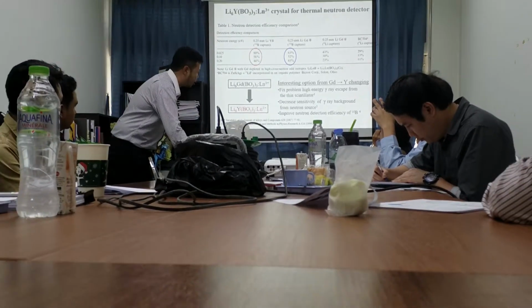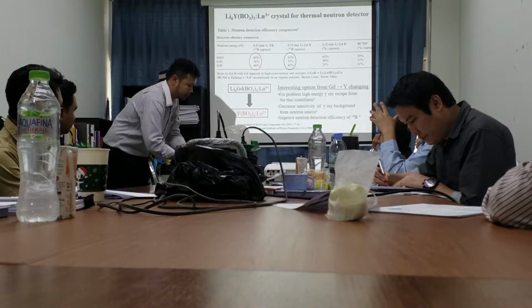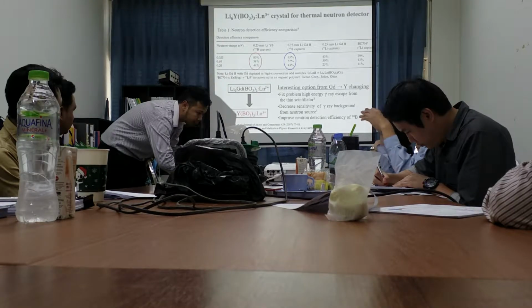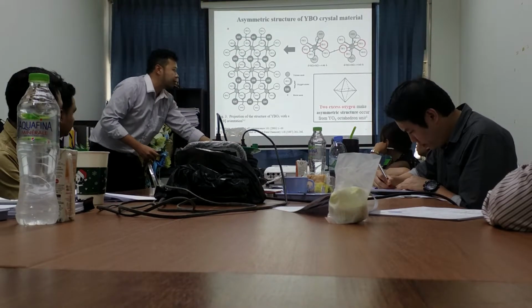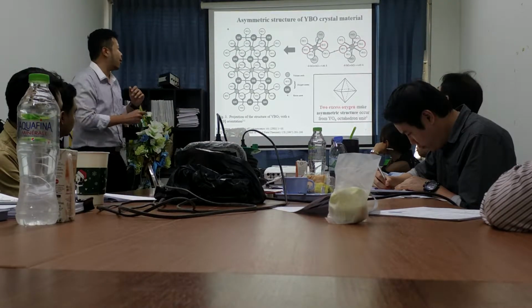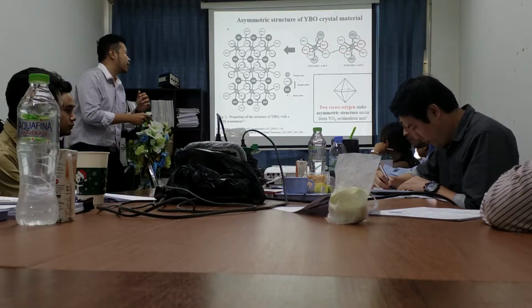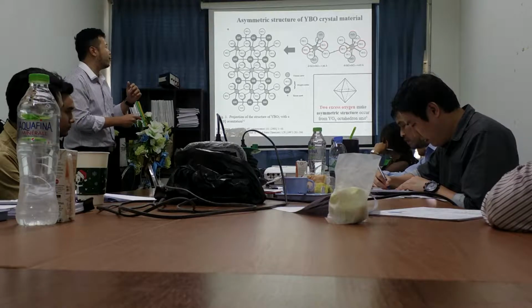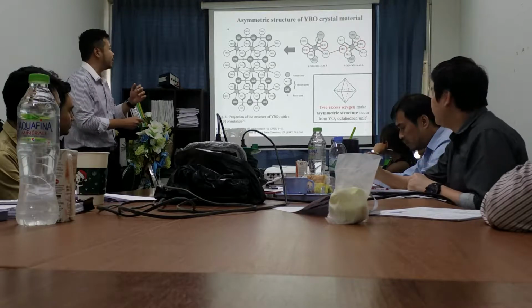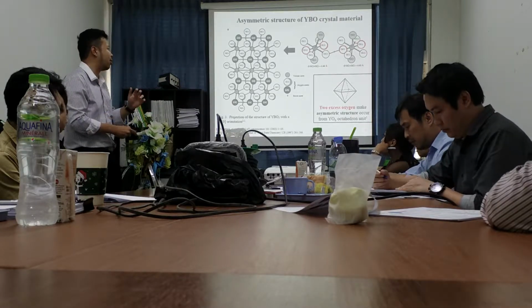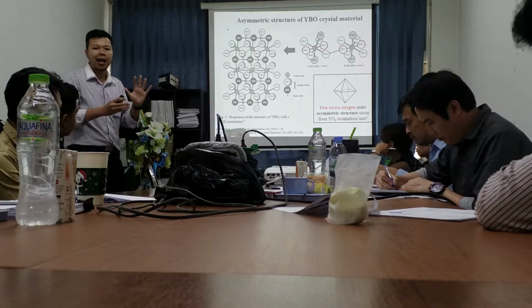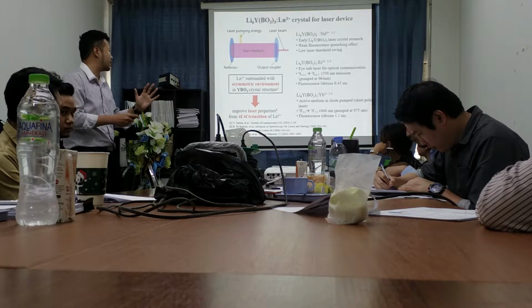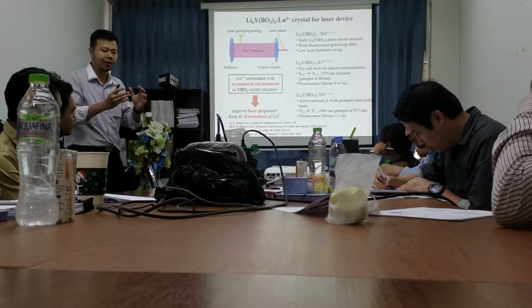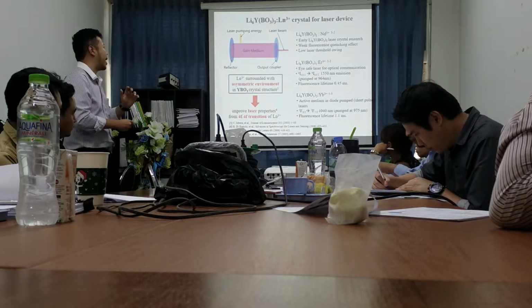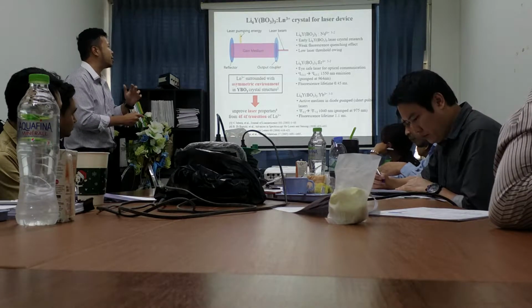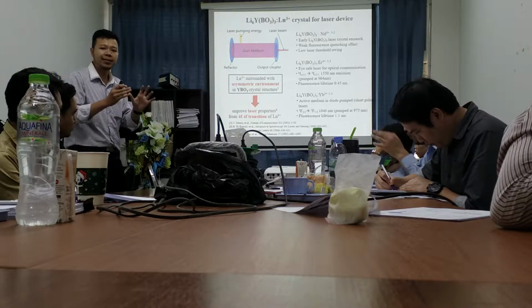Moreover, when we look at the structural unit of the yttrium oxide polyhedron, actually it has YO8. We found two excess oxygen that exist. These two excess oxygen make an asymmetric structure occur in the octahedral unit. Lanthanide ions like the asymmetric structure because it can improve and enhance the luminescence properties of the lanthanide ions. Therefore, lithium yttrium borate crystal was doped with neodymium, erbium, and ytterbium to study for laser application also.